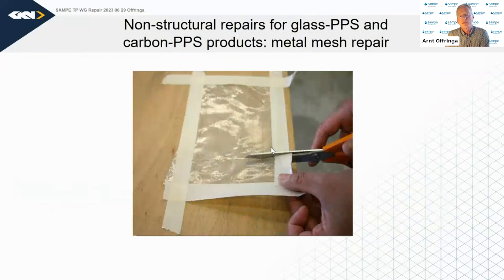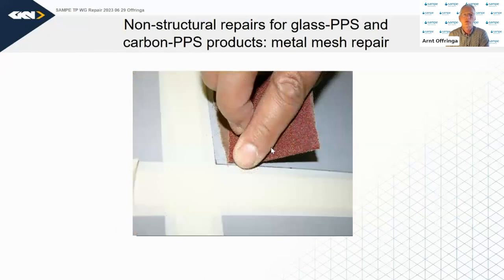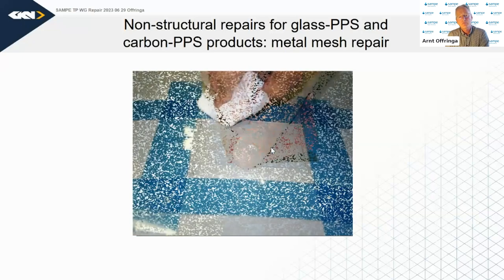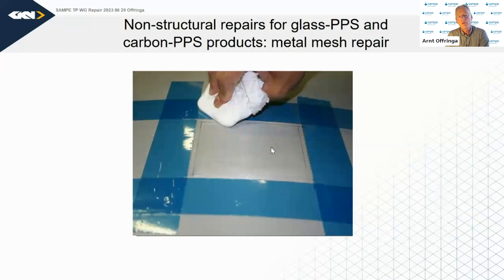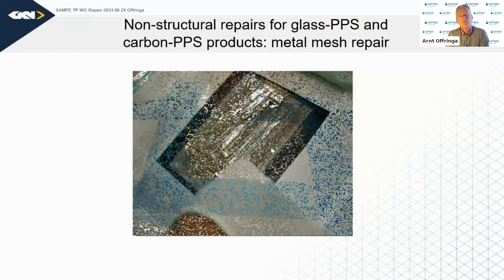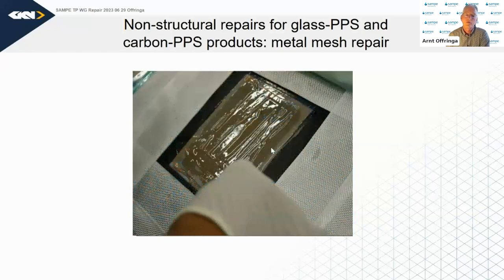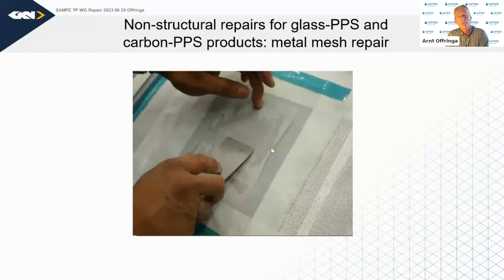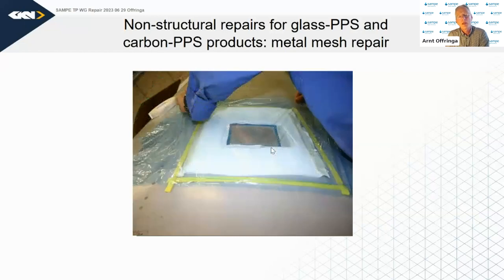So the way to do it is to cut out a mesh for the repair. So this is aluminum mesh. Then sand the area to be repaired, clean the area to be repaired, then apply a layer of epoxy resin on the area to be repaired, place the mesh and use a spatula to basically force out the excess epoxy resin, and then make a vacuum bag to get pressure on the repair.